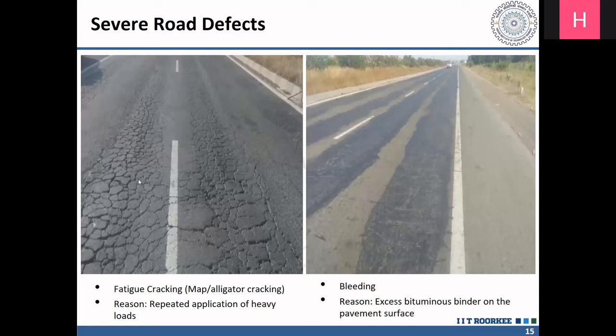Maybe if the existing pavement has a minor crack, then in such a case crack sealing would be the best treatment option. But from this slide, if you look at this kind of failure, fatigue cracking, it is very severe in nature. This kind of pavement section is the right candidate for taking up recycling. Even if we suggest crack sealing, it is not going to work at all.